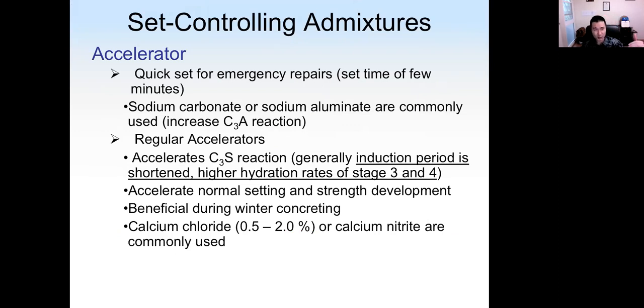All right. So for accelerator, we have two classes. The first one is called quick set. So that is for emergency repair. The concrete will set in a few minutes. The chemicals such as sodium carbonate, the function of that is to increase the reaction speed of C3A. C3A is one of the compounds which reacts the fastest. The hydration rate, number 1 is C3A, number 2 is C3S, then C4AF and C2S. So quick set increases the hydration speed of C3A, so the concrete will set in only a few minutes.